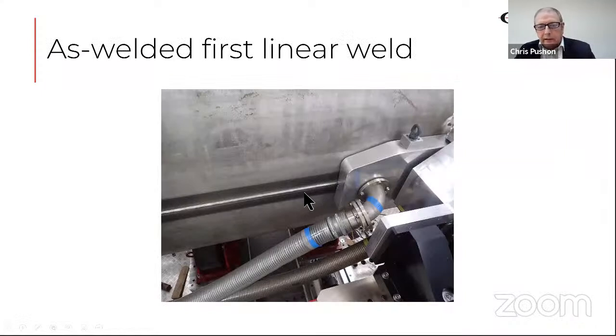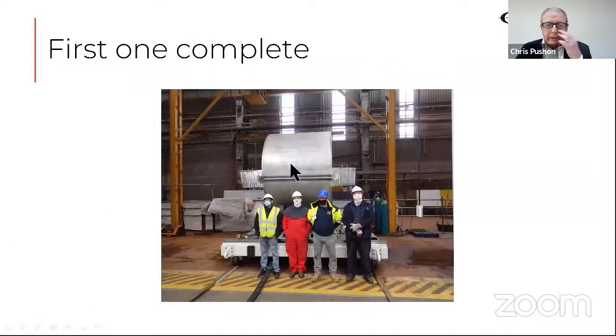Again, the linear seam was welded with a local vacuum head. And this is 60 millimeters thickness, 1.5 meters long. And the welding time for completion is eight minutes. And there's no wire, flux or gas shielding required. So the economics are quite strong. This is the first can welded.